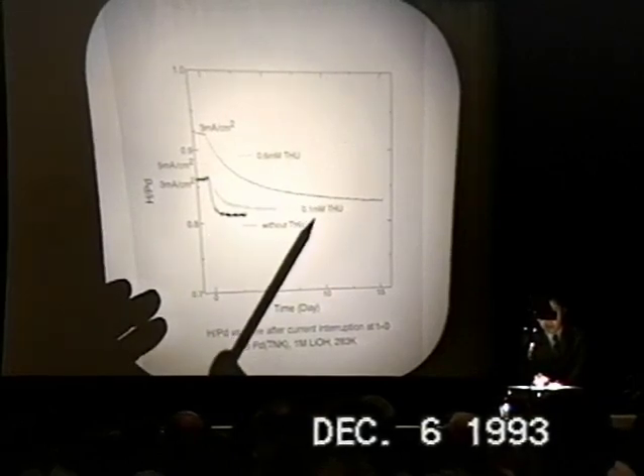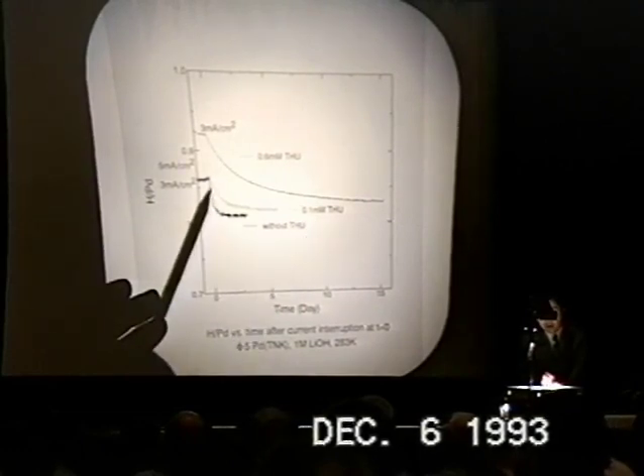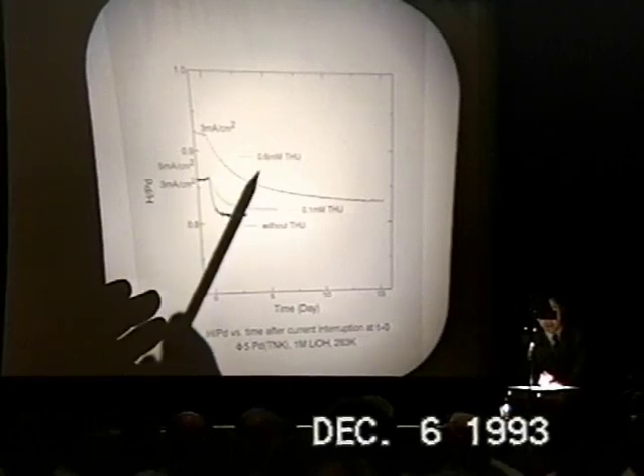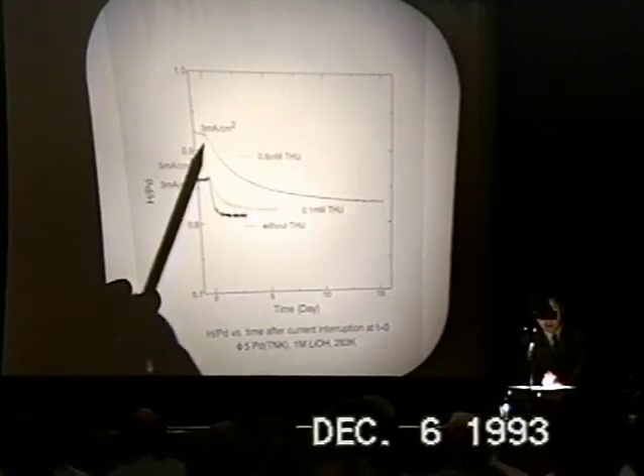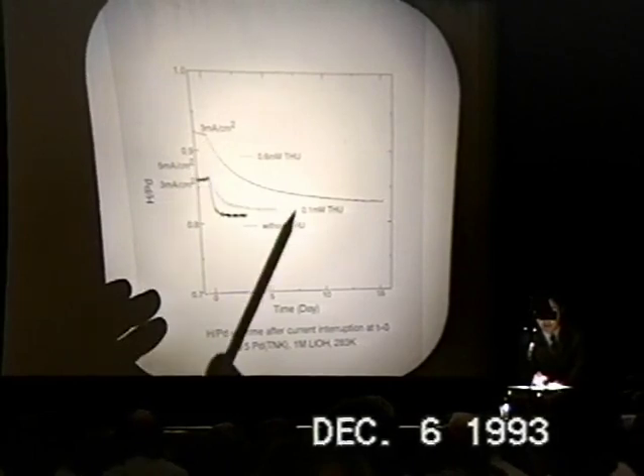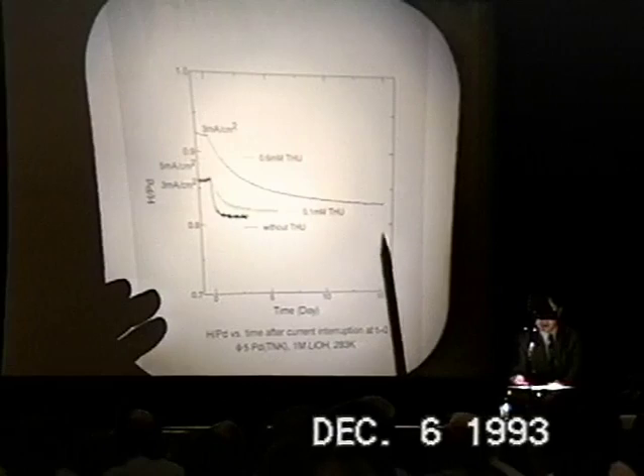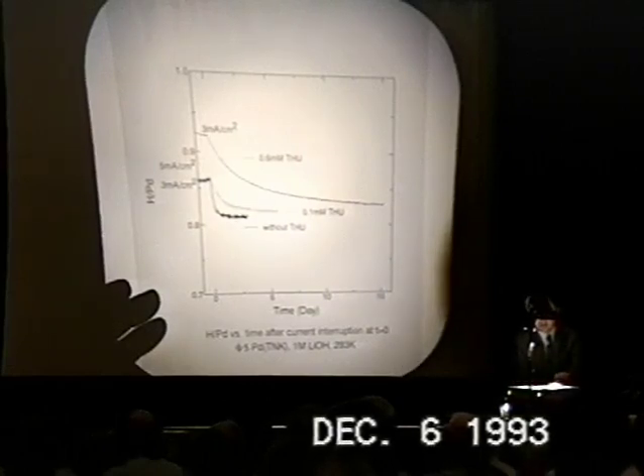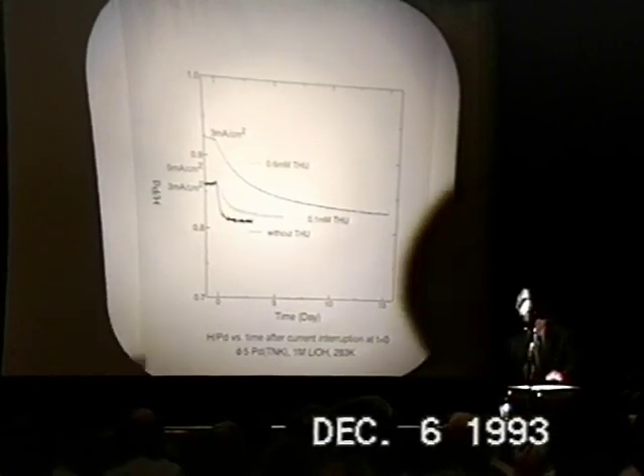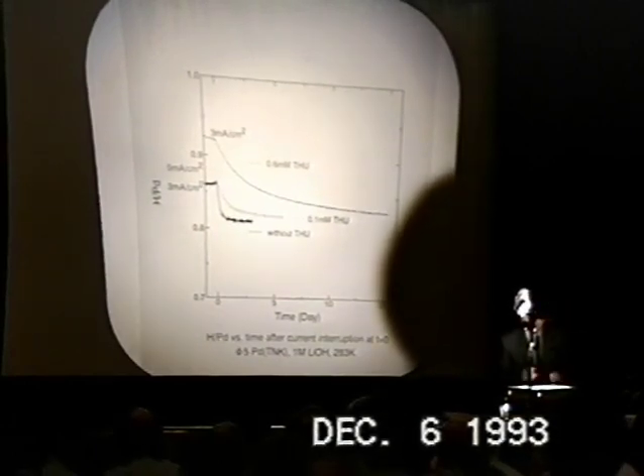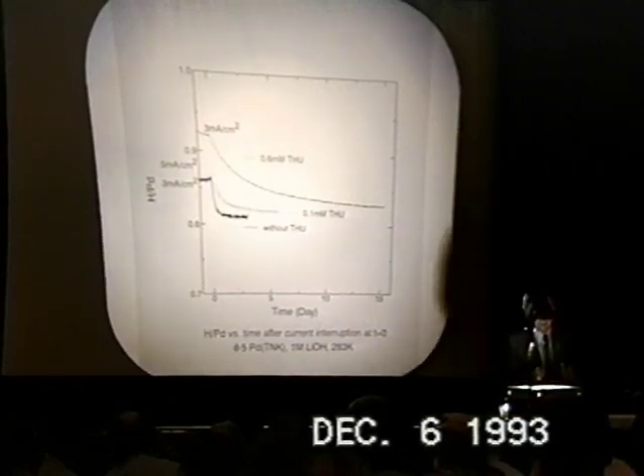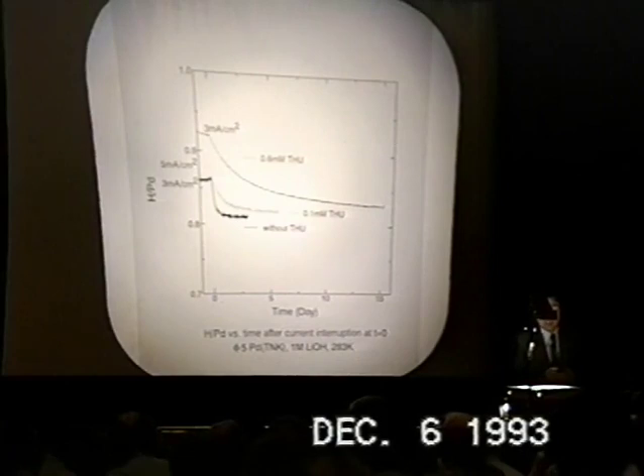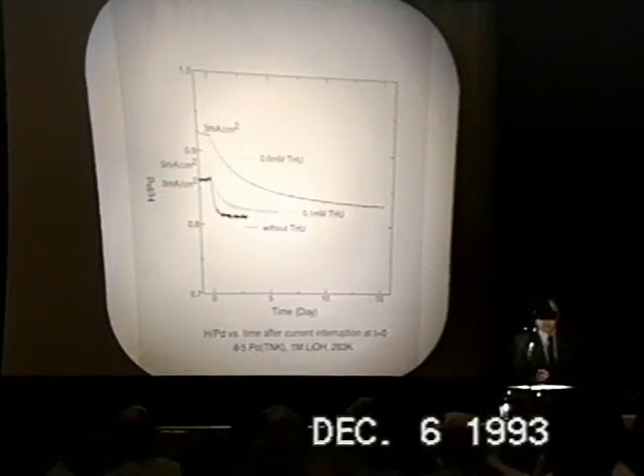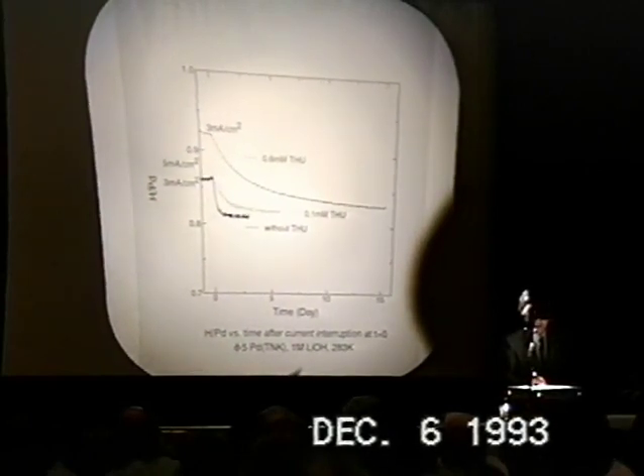But with 0.1 millimolar thiourea, the desorption becomes slower, and then with 0.6 millimolar thiourea, the desorption from the cathode becomes very slow. It is taking nearly 2 weeks and still not reaching the final steady value with this 0.6 millimolar thiourea. So this strongly suggests that the thiourea is actually retarding or poisoning the recombination step of absorbed hydrogen atoms, thus inhibiting hydrogen desorption from the hydrogen cathode. And I'm sure this is the reason why we have